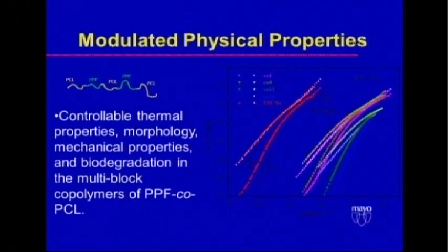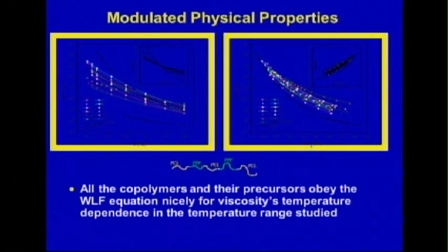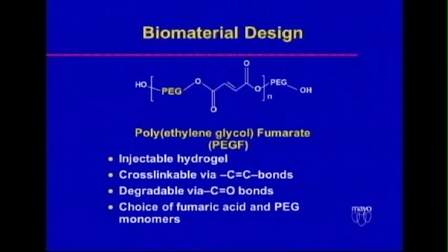The properties can change. We can control the thermal and morphology properties, et cetera. As you see on the right, the things that we measure for mechanical properties in our biomechanics lab, for which you can ignore the viscous component, we'll get a Young's modulus, et cetera. But for the polymers, we have to include the viscous component and measure the storage and loss moduli in a dynamic mechanical analysis rather than just, if you will, an Instron machine. And also the Williams-Landel-Ferry equation for viscosity's temperature dependence is followed very nicely by this series of polymers that Shanfeng made.